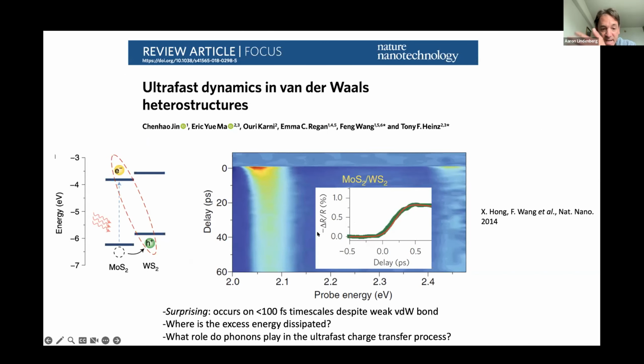Here's the data. These are tabletop transient absorption and transient reflectivity measurements. Essentially, you excite one of these heterojunctions, and in a rough sense you're probing the band filling. So you're looking at the population: when charges cross the interface, they fill particular electronic states, and this modulates the optical properties, the absorption, the reflectivity. The key experimental observation here was that this process is occurring on essentially time-resolution-limited dynamics. They're not even resolving it. They didn't have the time resolution to resolve this process. Follow-up measurements have shown that this process occurs much faster than 500 femtoseconds, on 100 femtosecond timescales and below.